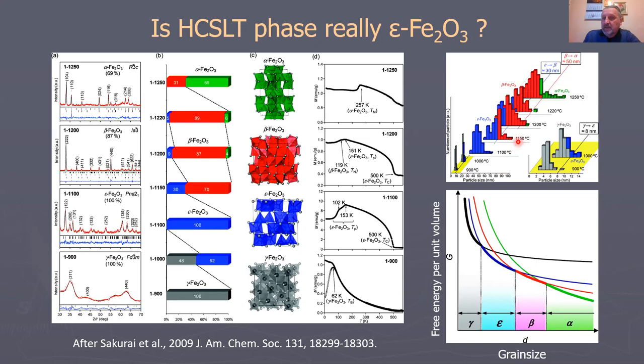Once again, in this very perfect synthetic route, particles larger than 30 nanometers became unstable and transformed first to beta iron oxide, and finally to hematite.